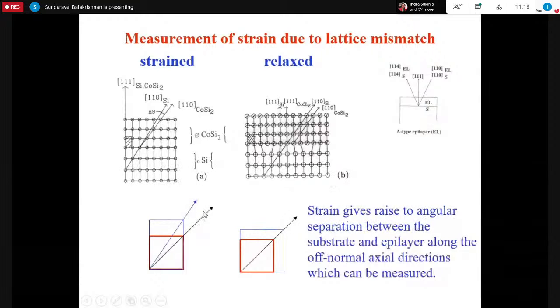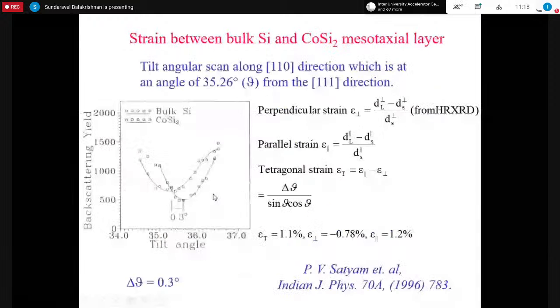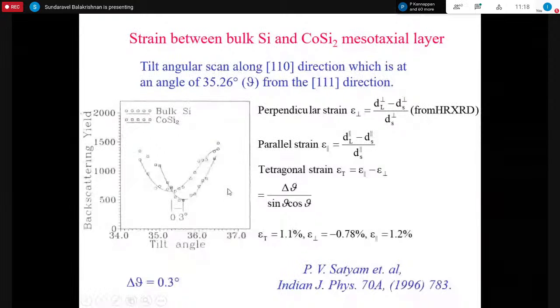much is the strain, and the strain whatever we are determining is tetragonal strain. Tetragonal strain is the difference between parallel strain and perpendicular strain. So, for example, in silicon and cobalt disilicide, the normal direction is 111. We go for the 110 direction, which is at 35.26 degree. The 35.26 degree is theta, and delta theta here we observe is 0.3. One curve is for silicon, another is for cobalt. So from this we can find how much is the tetragonal strain, and if you know the bulk modulus and all, using channeling itself we'll be able to find other strains, perpendicular as well as parallel.